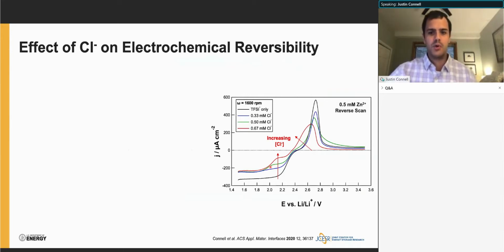As we play around with the chloride concentration, we see two very interesting things happening. The first is that as we increase the chloride concentration, the magnitude of the current density associated with this first reduction plateau decreases, suggesting that in order to access the full current density accessible in the system, you have to go to higher and higher overpotentials, more and more negative potentials.